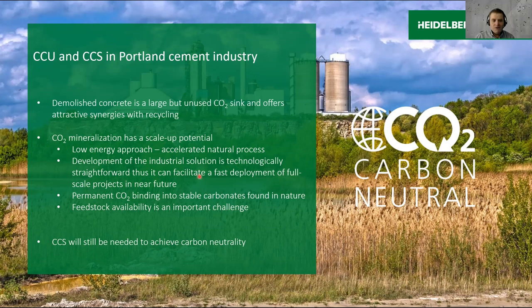We are, of course, binding a lot of CO2, and theoretically, we can bind during the carbonation of RCP all the CO2 emitted during the clinker production from limestone decomposition, and on top, we can use this carbonated material as a new SCM, which further allows us to reduce the clinker content in the cements. Okay, and those are the most important conclusions.